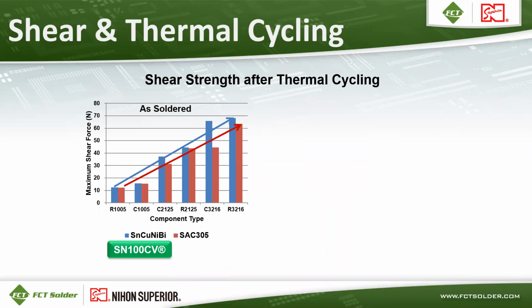What about shear strength after thermal cycling? Here's a chart of maximum shear force on the y-axis with different types and sizes of components on the x-axis. Again, we have SAC305 in the red bars and SN100CV are the blue bars. And this is data as soldered. You can see SN100CV has slightly higher shear force than SAC305, but they both increase as you go to larger size components.